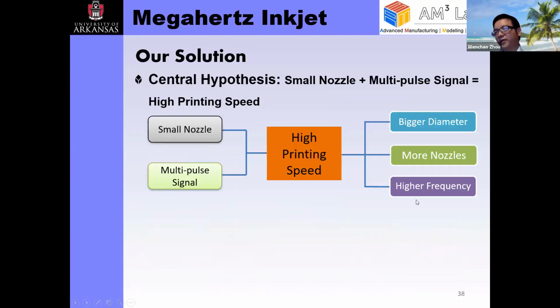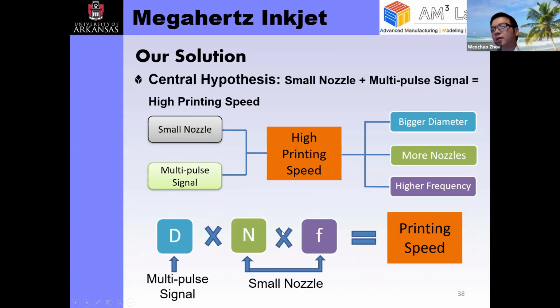So our idea is, can we use a smaller nozzle to produce a larger droplet? Because if we can do that, we'll be able to pack more nozzles, and we'll be able to get higher frequency. Our hypothesis here is that we can use a multi-pulse driving signal to drive more liquid out in order to form a larger droplet size, with smaller nozzles, while maintaining very high frequency. So this is our central hypothesis. It's sort of one stone, three birds. You're hitting these three factors of printing speed at the same time.